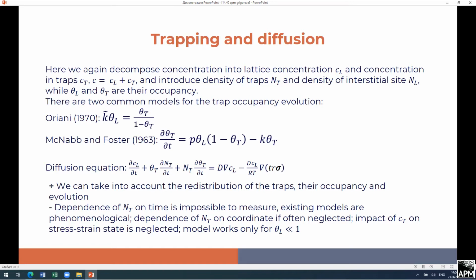Another common way to consider trapping is again to decompose concentrations in the lattice and trap, and we also introduce the density of traps and the density of interstitial sites. So we can say that if we have occupancy, we can multiply it by the density of our traps or sites and have the concentration.